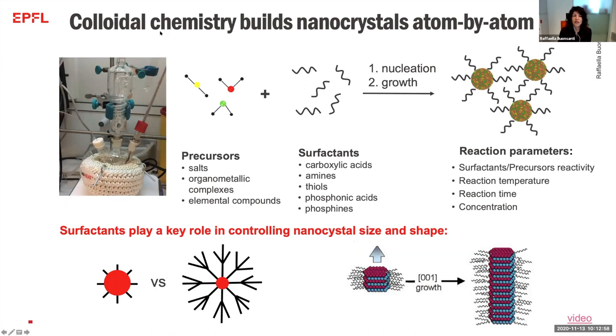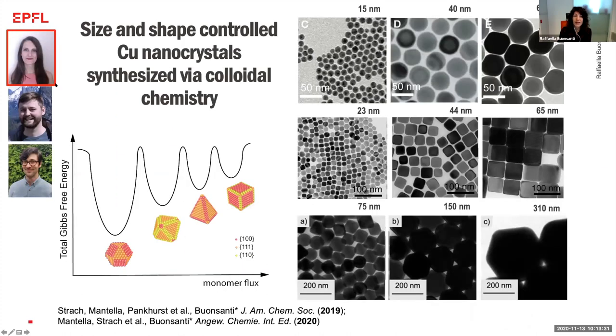So what we use is colloidal chemistry, which allows us to build nanocrystals atom by atom. We use a three-neck flask, and we basically properly choose precursors and surfactants. We modify some reaction parameters so as to obtain our final nanocrystals. And these surfactants actually play a key role in the synthesis because, for example, by changing the steric hindrance, we can change the size, or by changing the binding energy to different facets, we can also change the shape. You will hear more about this topic from my student Valeria, who will give a presentation soon after me. She will provide you with the details about this work.